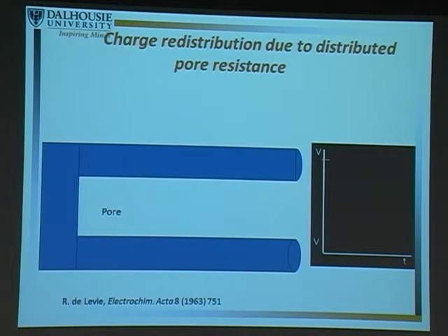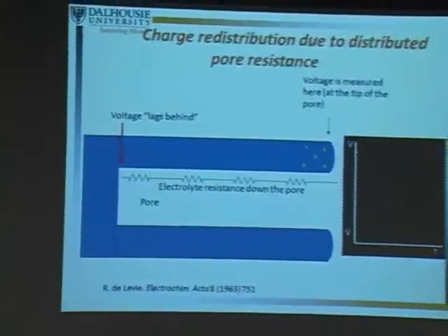So what I have here is a cartoon of a pore, and so we would have electrolyte in the pore. These are the walls of our carbon material. When you charge up a supercapacitor, in fact any porous electrode, the potential that you measure is measured at the tip of this pore. And so if you want to charge a porous electrode up to, say, a voltage of 1 volt, then the tip of this pore will be at 1 volt, but deeper in the pore, the voltage lags behind. So that potential is going to be much lower, and it'll depend on the shape and length of your pore. And so this is because of the electrolyte resistance in the pore. Ions require a certain amount of time to move deeper into the pore. So you charge the tip first, and the base of the pore charges much slower.